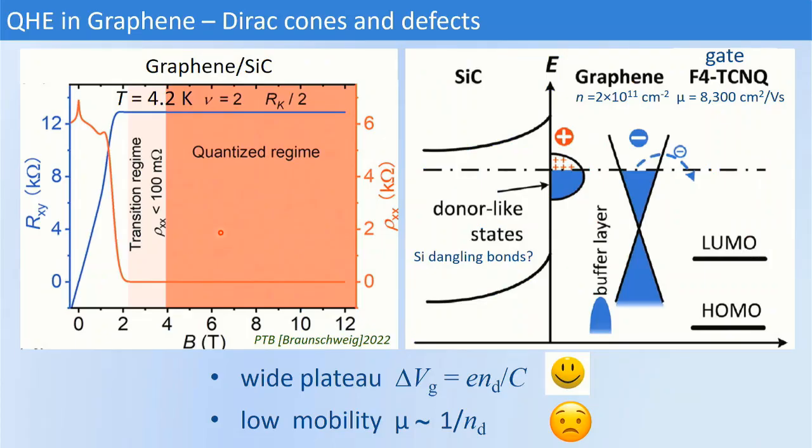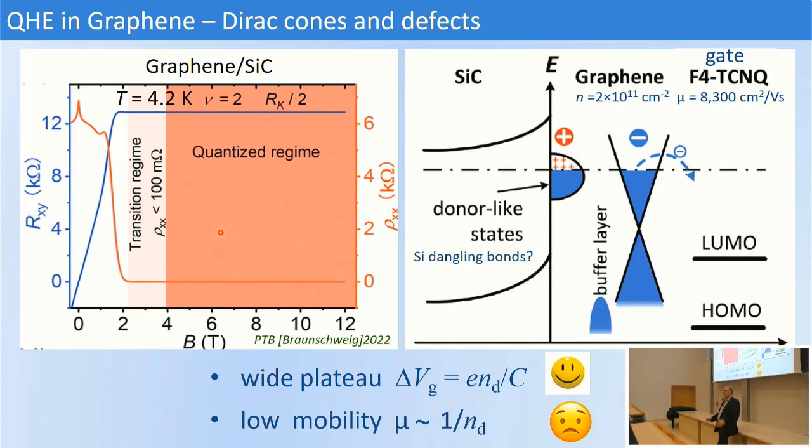So we go to something which has very low effective mass. Some of you remember graphene. Graphene has a linear dependence of energy on momentum, which means that near the bottom, near this charge neutrality point, the effective mass goes to zero. So in graphene we expect that this quantization will be better, and this is shown here, where indeed this plateau appears at lower magnetic field,